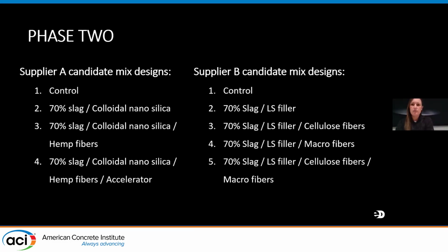Results from phase 1 of both suppliers were promising, suggesting that a high volume slag shotcrete mix was possible. We then selected the mix designs that had the highest potential for success, selecting those that performed most similarly to the control mix. Those mix designs all included 70% slag and different combinations of colloidal nanosilica, hemp fibers, different percents of limestone filler, cellulose fibers, and macrofibers.